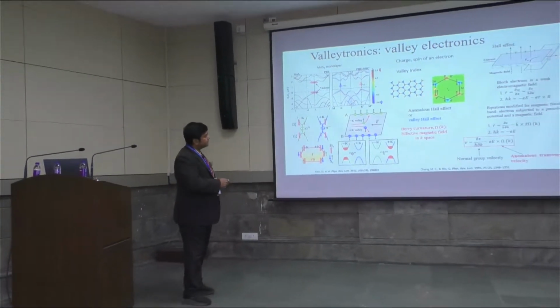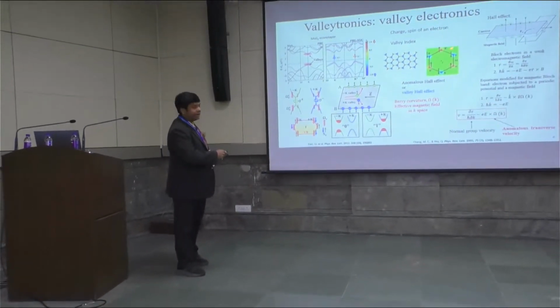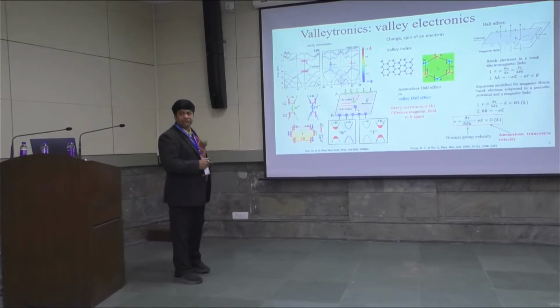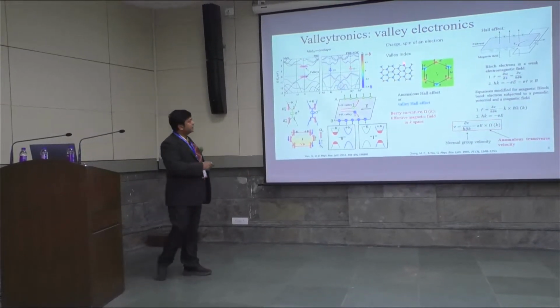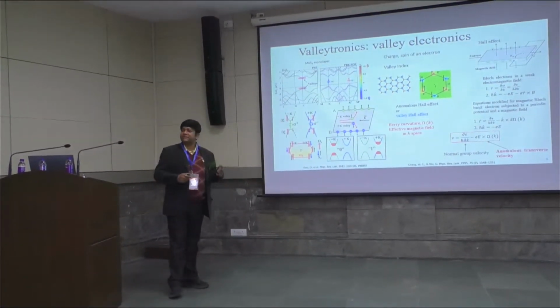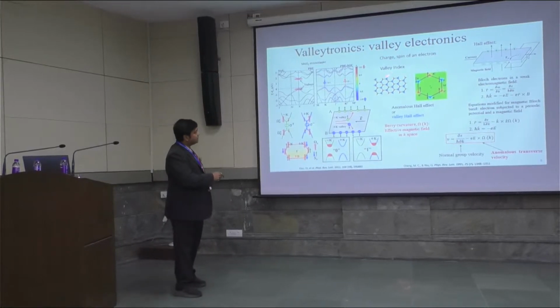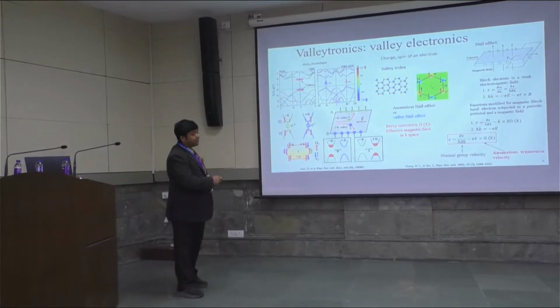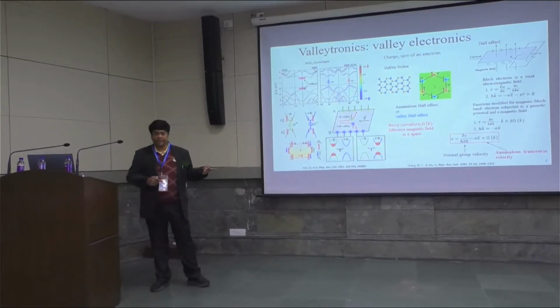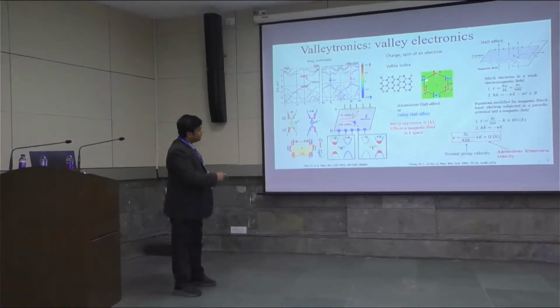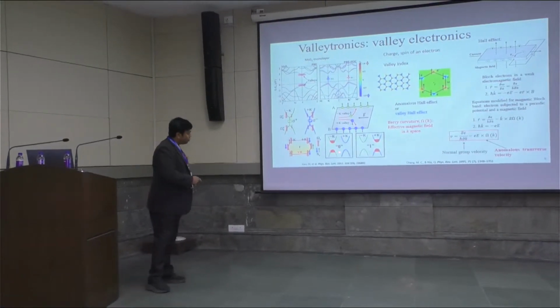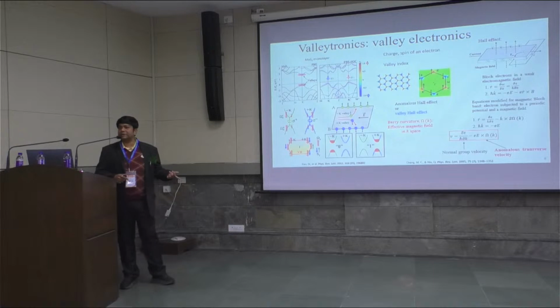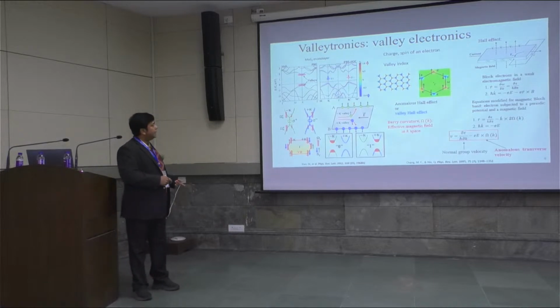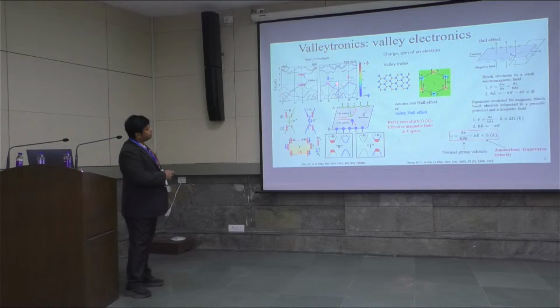Therefore, the opposite spins are locked to these momentum values. This K and K prime become distinguishable in MoS2. In a single layer crystalline graphene lattice, all the atoms are carbon, and therefore K and K prime are not distinguishable in graphene. So this K and K prime, or K and minus K, can play the role of zeros and ones in electronics, and therefore can be used to store, encode, and process information. And also you can see in the band structure plot here, opposite spins are locked to these momentum values.